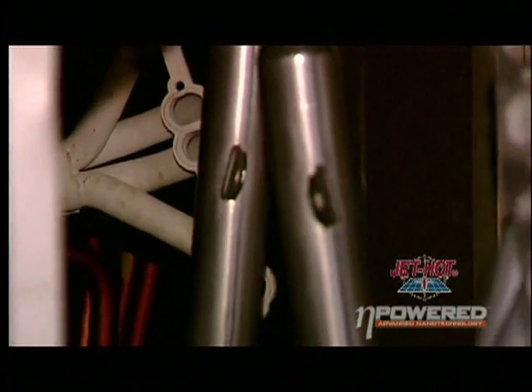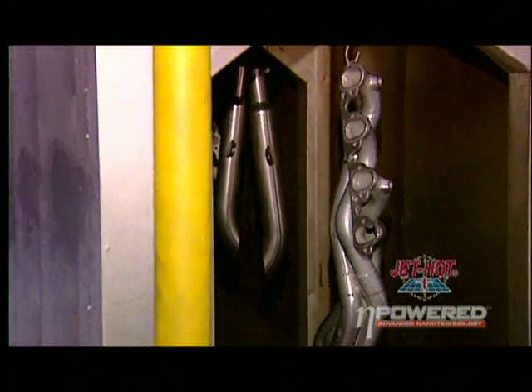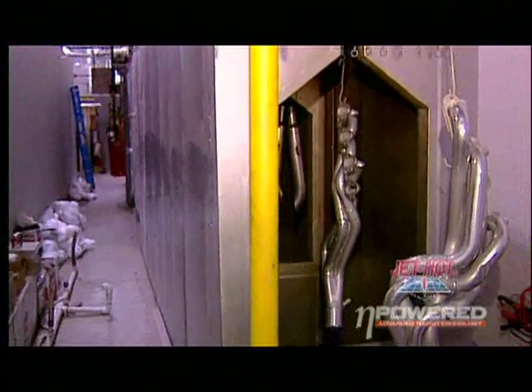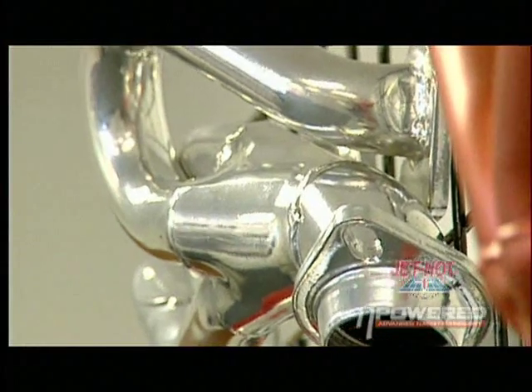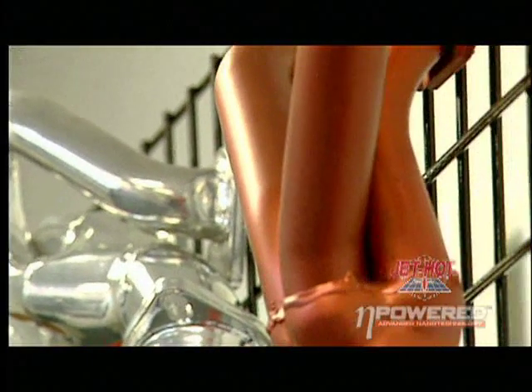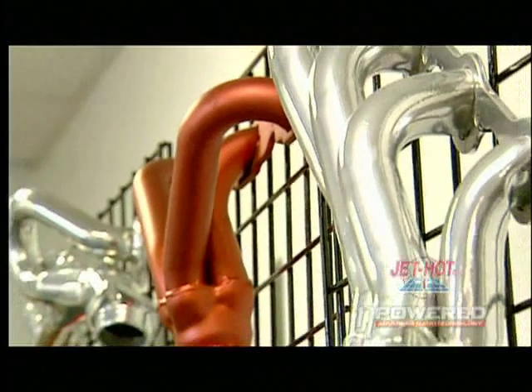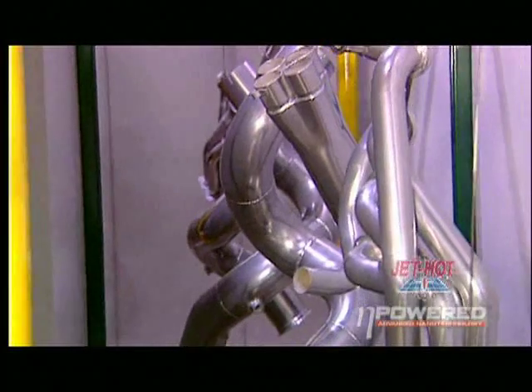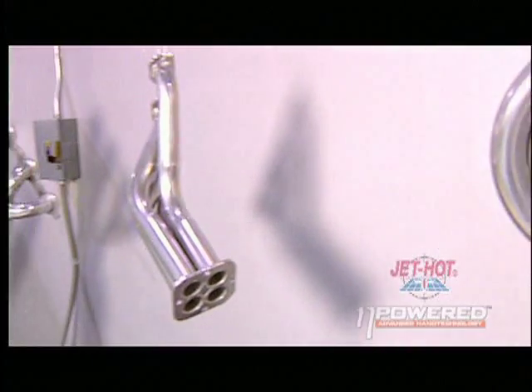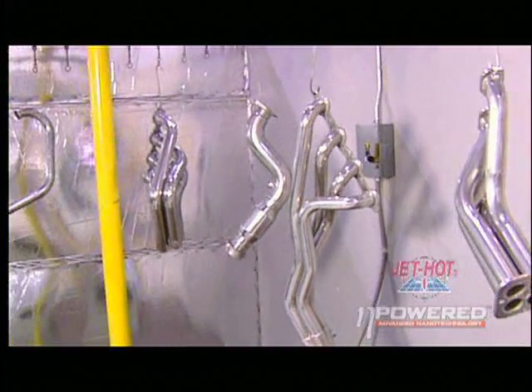This does more than just dry the coating. It chemically activates it. In fact, it is so active that if you scratch your Sterling coated header, the coating will span the gouge to protect the substrate for an extended period of time. Here we have a header coming through our process now. Experts agree that the result is amazing.